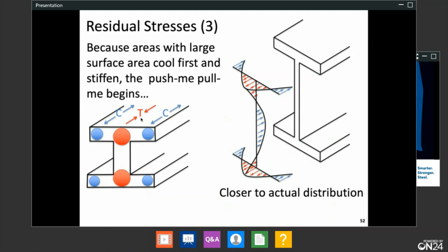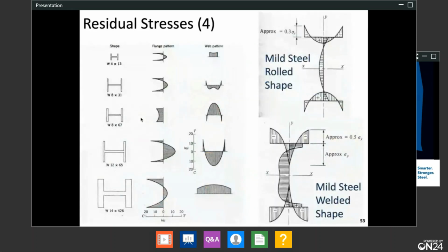Sorry. But you end up with a portion of the cross-section in compression and a portion in tension. Right? And the actual distribution looks something like that. Or here are some pictures. It varies how much that residual stress is from cross-section to cross-section. And, of course, whether it was rolled or welded can impact the residual stress pattern. So it's a complicated subject. And the point I want to show you is these residual stresses are not small. They can be on the order of 30 to 50% of the yield strength. So remember, Craig, when I was telling you, you thought you bought a perfectly straight column, you realized you didn't. You also bought a column that may have some residual stresses already built in it.